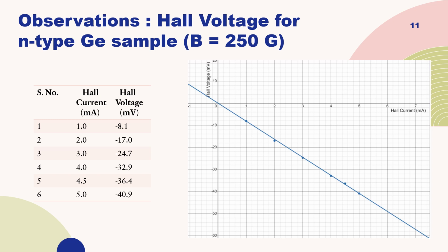So here are the observations for Hall voltage for a n-type germanium sample at a constant magnetic field B equal to 250 Gauss. We can see that it's varying linearly with the Hall current, but it's decreasing with respect to the Hall current, unlike the p-type germanium sample. So from these two graphs, we can see that the Hall coefficient is positive for a p-type sample and is negative for an n-type sample.